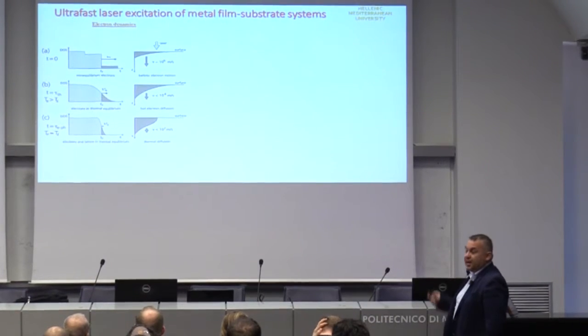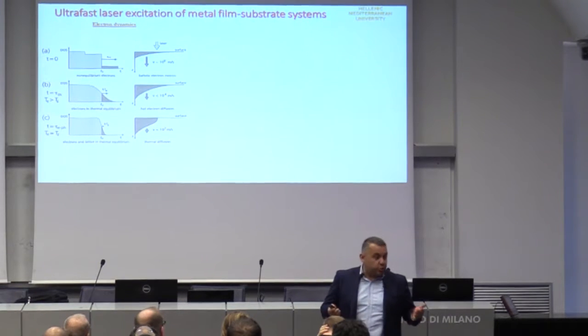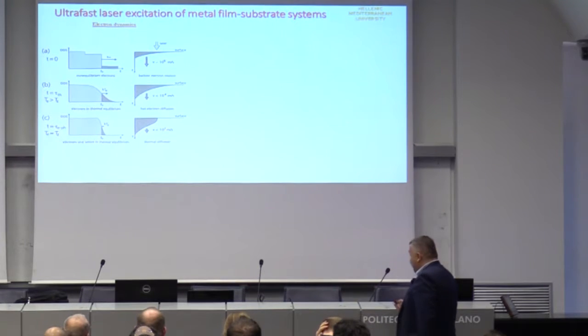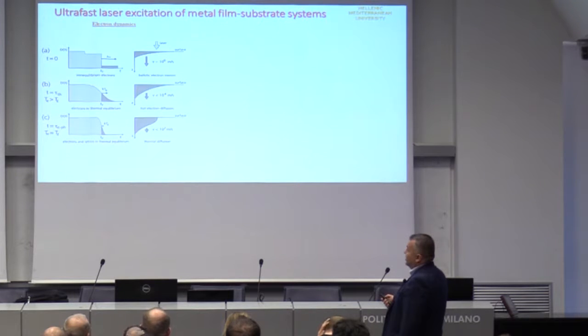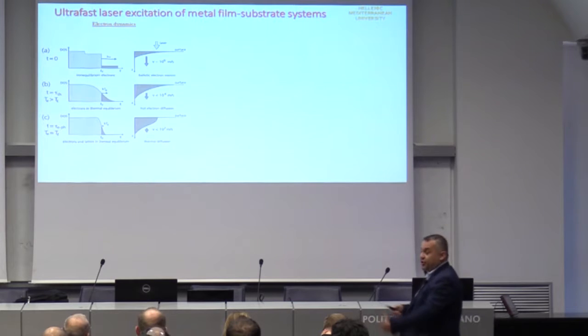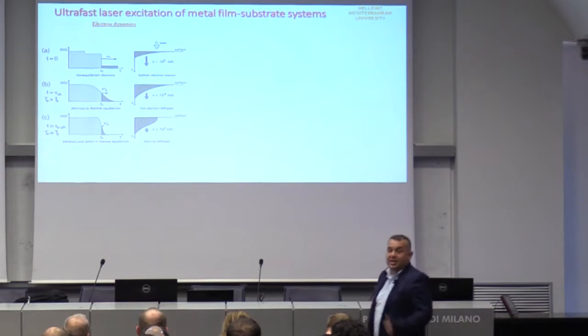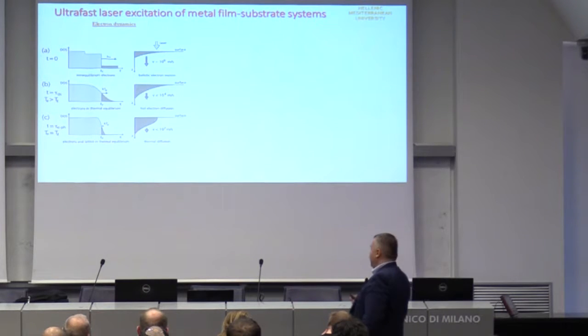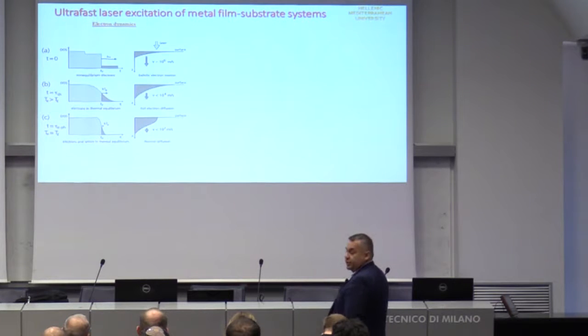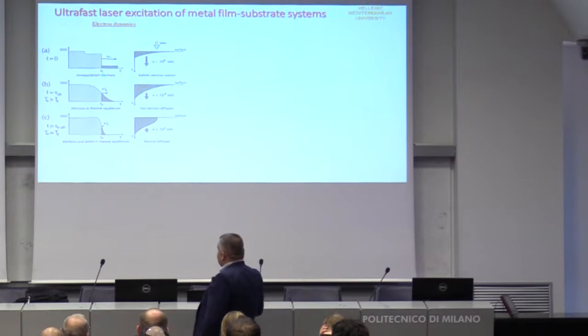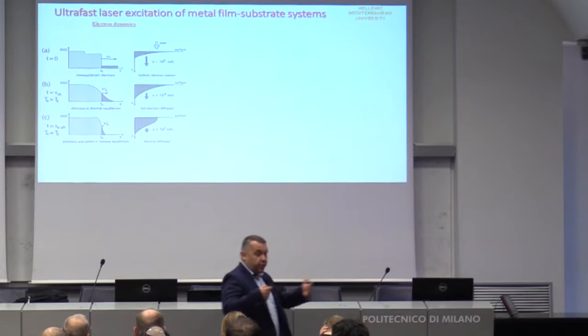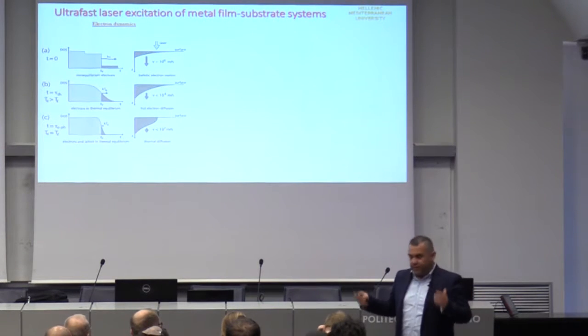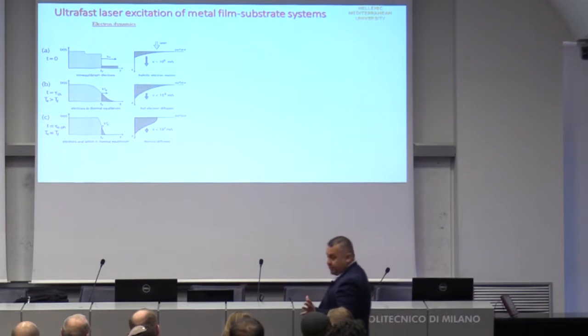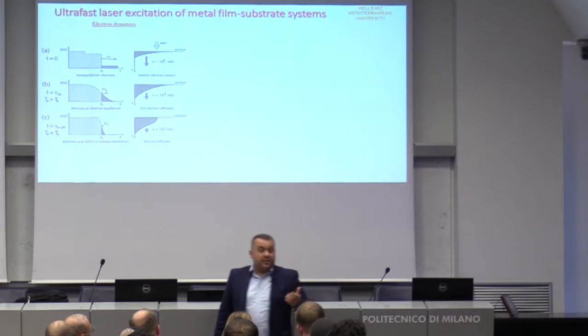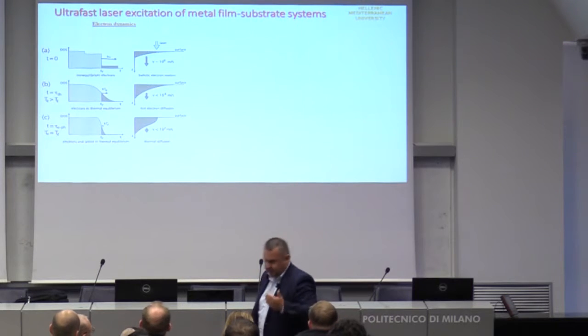For example, first of all, electron dynamics. Illumination by a femtosecond laser on a metal surface, which is a very good transducer from optics to acoustics. We have electrons initially which are non-equilibrium. This is the Fermi distribution of electrons in the initial time scale, where some electrons go from here to here, so there is a non-thermal electron gas in the illumination area of the metal. Then there is a fast thermalization with a different temperature at the Fermi level. And then there are electrons in thermal equilibrium. After the initial non-thermal electrons, there is also electron-electron and electron-phonon interaction. And finally, we have electrons and lattice in thermal equilibrium, and there is a temperature of the lattice, which actually produces the strain that propagates inside the material.